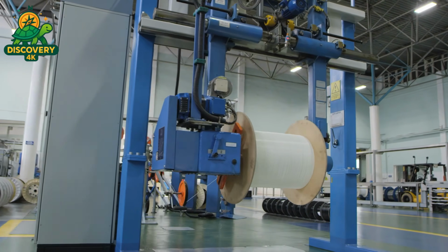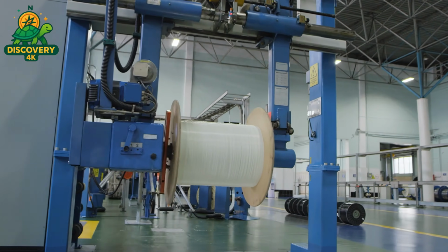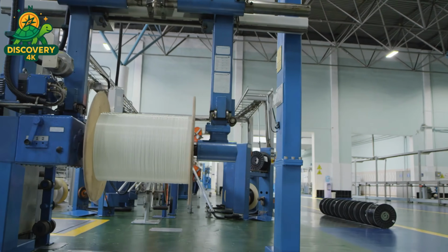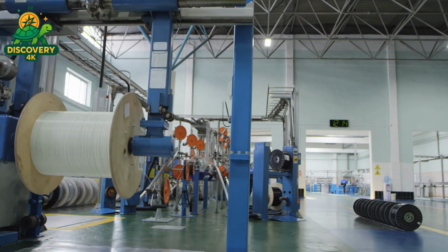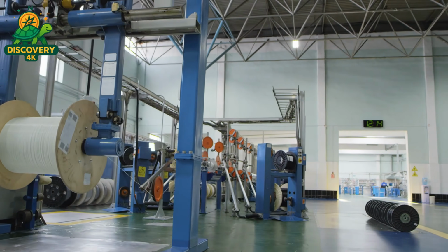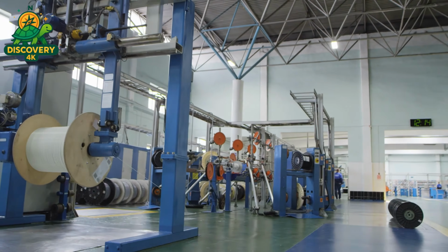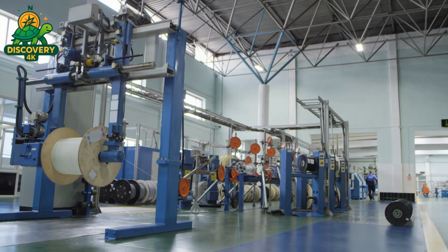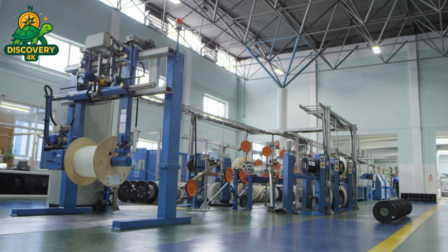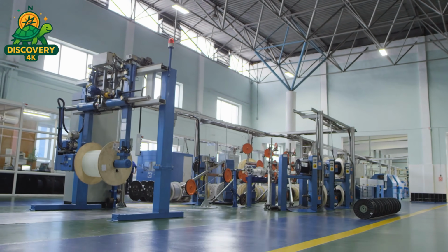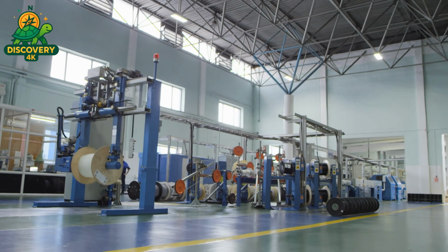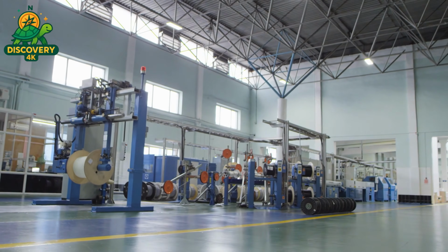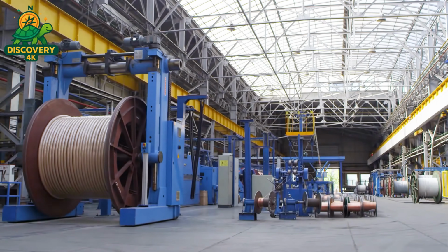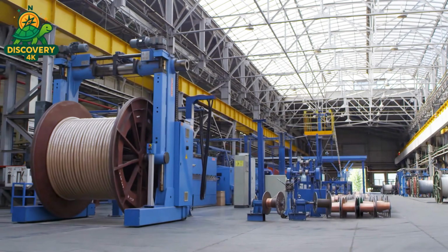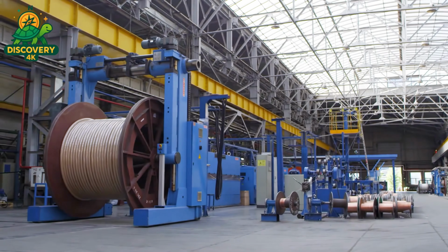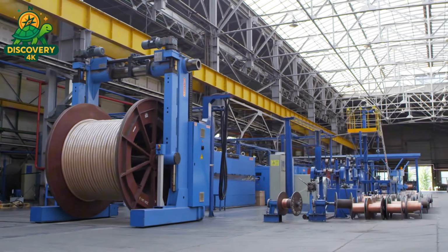Before a single cable leaves the facility, it must prove itself. Every batch goes through rigorous testing in specialized labs, each test designed to simulate a worst-case scenario. High-voltage dielectric test, subjecting cables to 1000 plus volts to verify insulation integrity. Conductor resistance test, ensuring the wire carries current within strict ohmic limits. Flame retardancy test, burning sections of cable in vertical chambers to ensure self-extinguishing properties. Cold bend and impact tests, flexing the cable after freezing to -40°C.